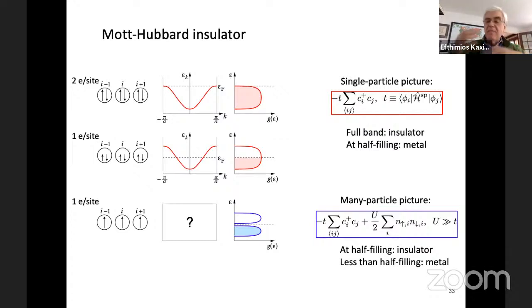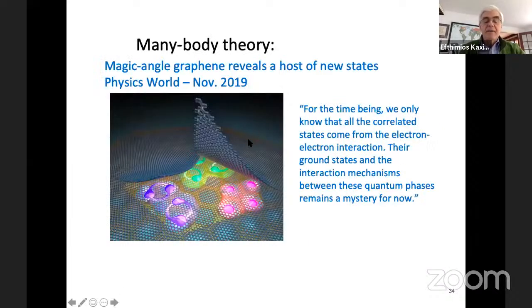Up to now, we've been talking about electrons behaving as independent particles. Now you have to have a correlated electron system where each electron sensitively depends on the behavior of all the other electrons. So in order to capture this behavior, you have to go beyond the density functional theory that I was describing earlier. So this requires a so-called many particle picture, many body picture. And this behavior here, where you develop a gap at half filling of the band, is referred to as a Mott Hubbard insulator. So this is difficult to capture. That's why it generated a lot of interest and is quite challenging.